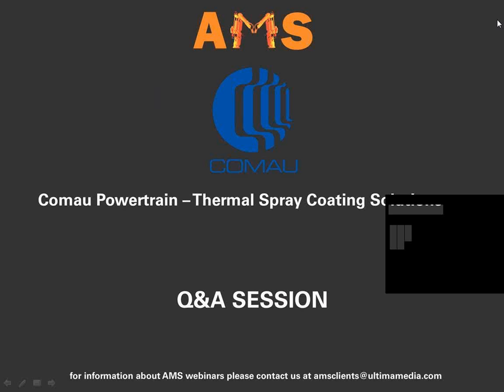If that was the question, the only other item I can think of is if you're asking 1 and 2, we have a single torch system and a dual torch system. The dual torch system allows us to coat 2 engine blocks at a time. The reason that we do 2 blocks instead of working 2 torches on 1 block is the ability to mask between the 2 torches so that we don't spray accidentally into the second torch. Within the same package of an LS100, we can package 2 torches and make it an LS200, and that provides effectively twice the output.